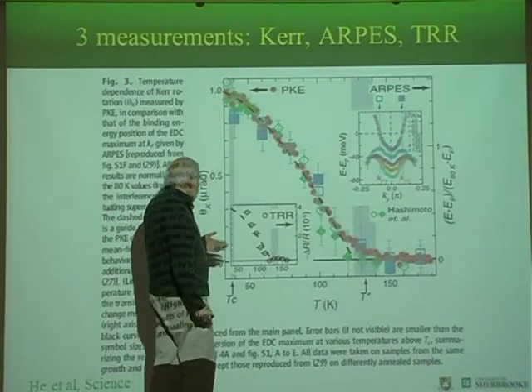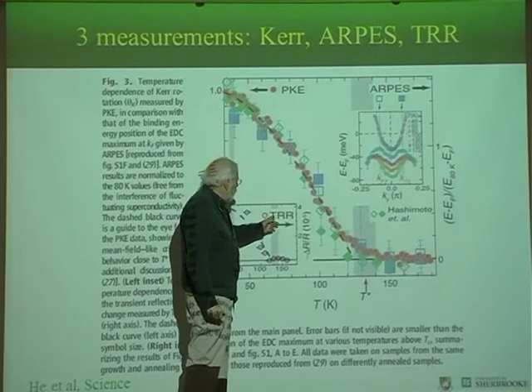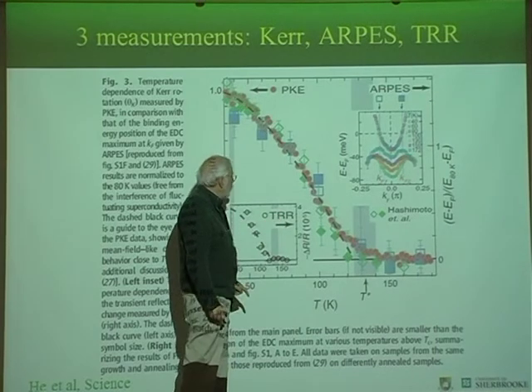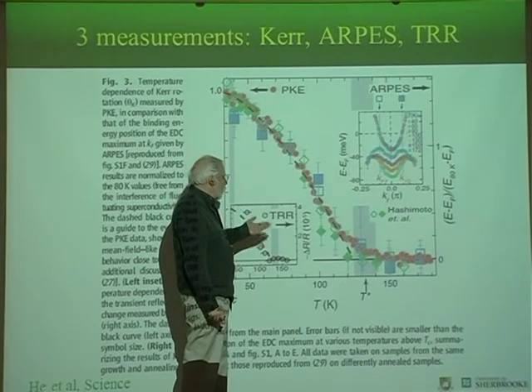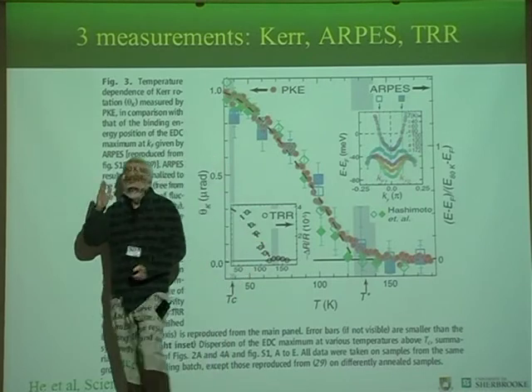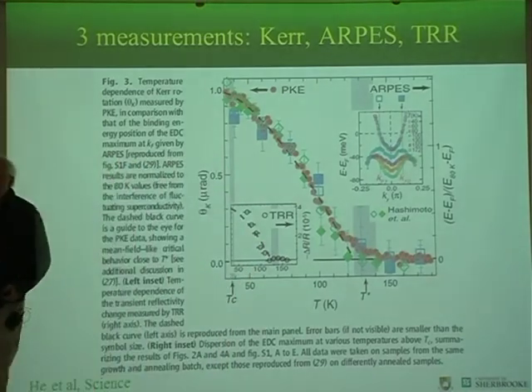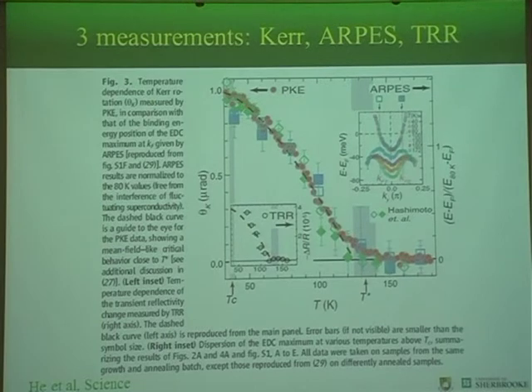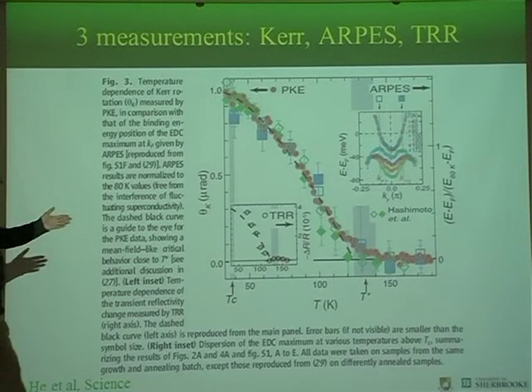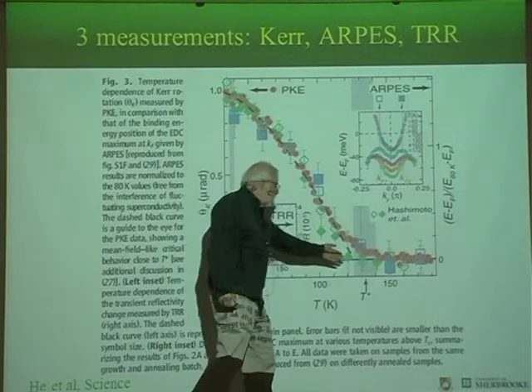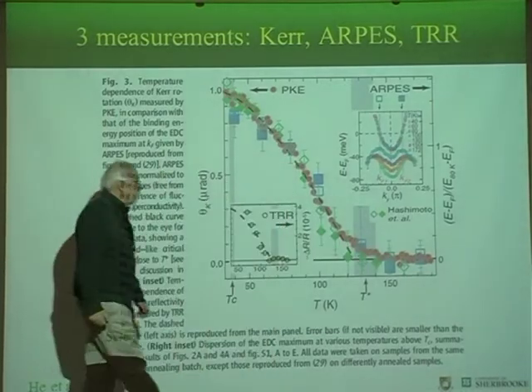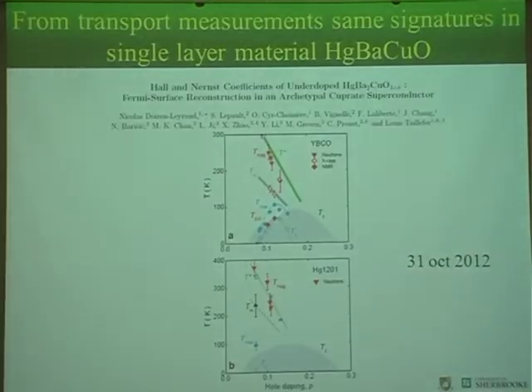And then the other experiment is time-resolved reflectivity. And the third experiment is the Kerr effect. So what is the Kerr effect? You send polarized light, and then it comes out with the polarization that is shifted, that is rotated a little bit. So you see that there seems to be a real phase transition at this point, and we know now that it corresponds to this charge density wave.